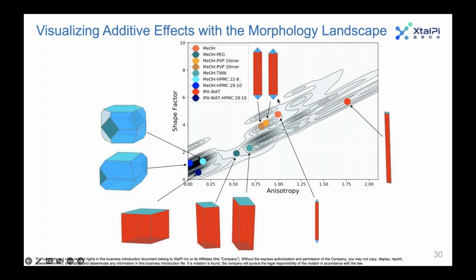And then we see down in this other region of the morphology landscape, the simulations that yielded much more prismatic or box-like structures. So remember, the morphology landscape suggested that prisms were a likely morphology for metformin HCl. And by using polymers, you're able to access that region of the morphology landscape. So by tweaking the experimental variables, you're able to significantly modify the morphology and obtain something that's much more desirable from a process standpoint.